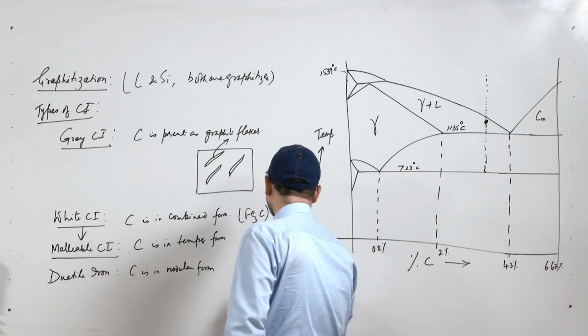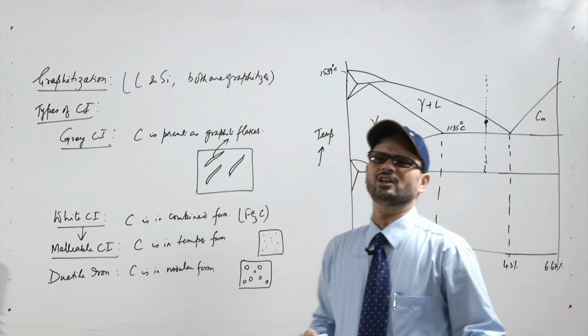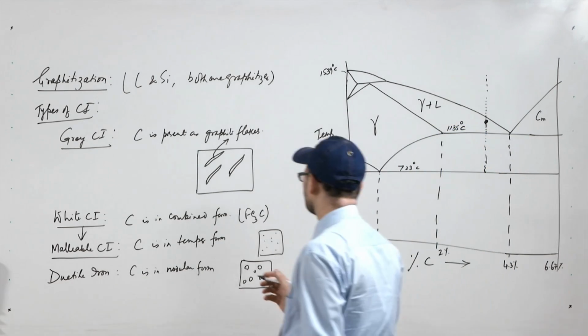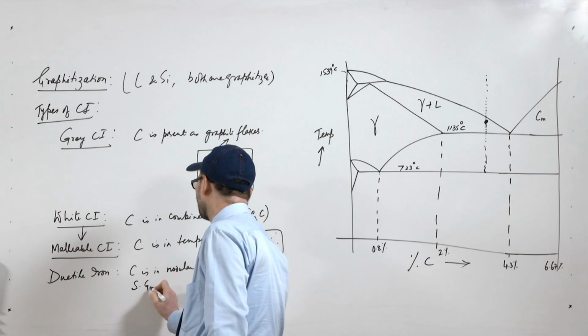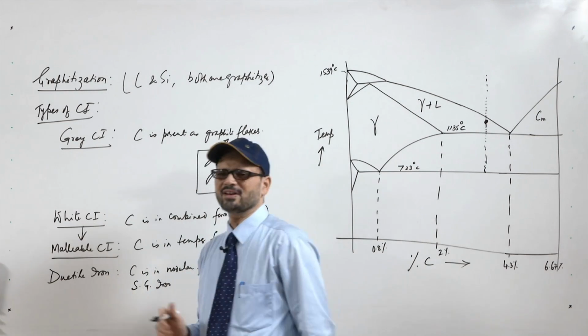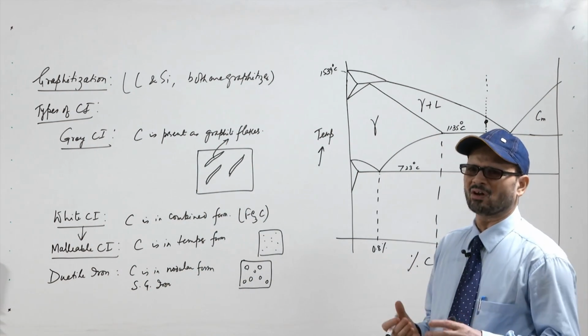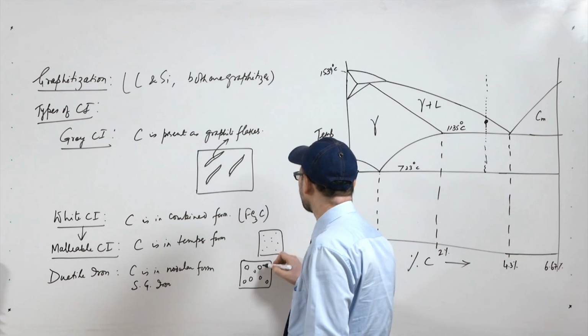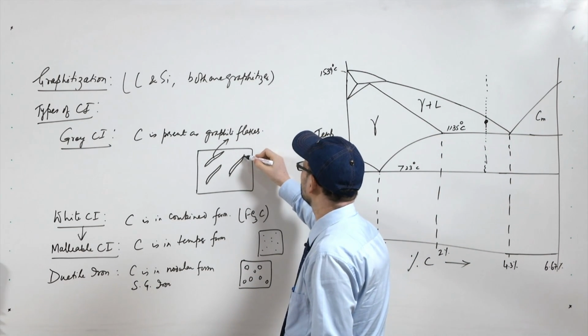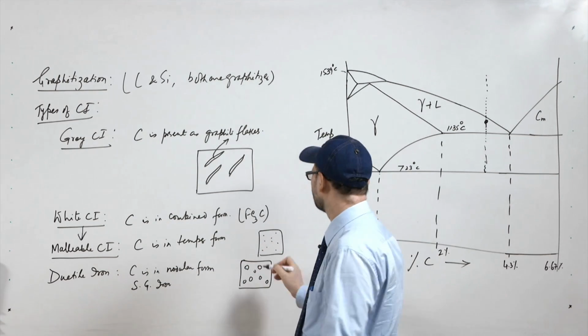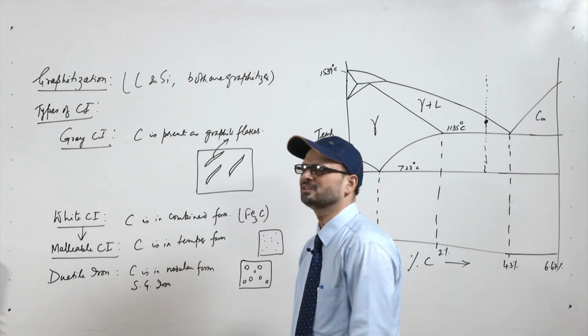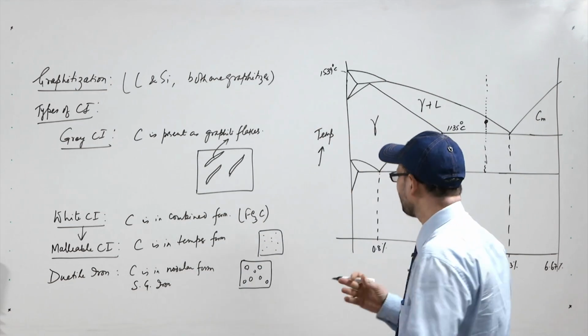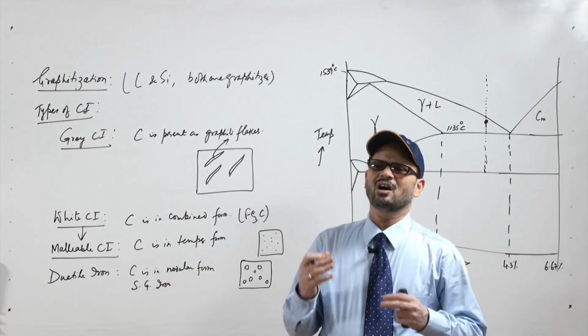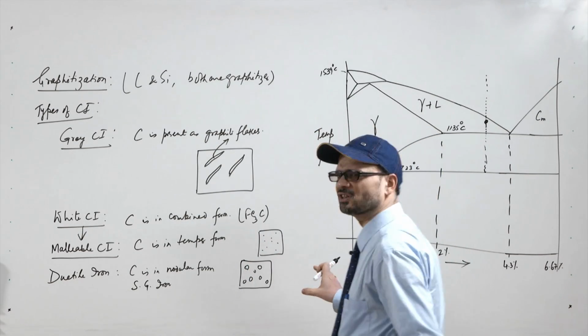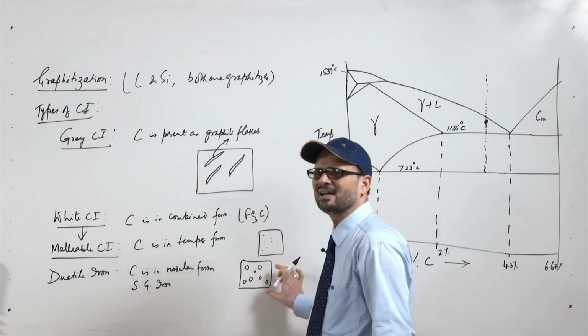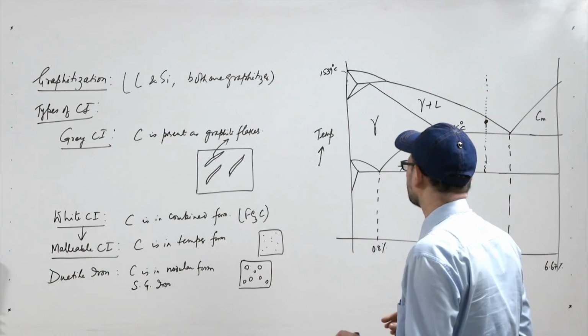Because of the presence of these graphite nodules, it is known as nodular iron, or it is also known as SG iron, spheroidal graphite iron. So, it has a very good combination of properties. Because of these nodular shapes of graphite, the adverse effect which we get in grey cast iron because of the pointed ends is gone, and so its properties are quite better. We can get it by magnesium treatment. There are many ways of doing the magnesium treatment in the case of ductile iron, and we get good properties of ductile iron.